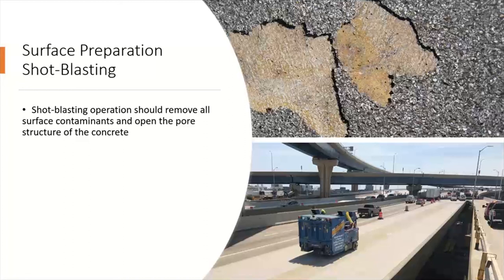The second thing that we noticed, and you might not know, but that amber color, we weren't 100% convinced that the first layer of the thin polymer overlay was mixed a little bit off ratio. But when you picked it up, you could poke it with a key or a fingernail, and you can see that first layer was soft. The second layer was hard, it was fully cured. The first layer wasn't. So two things went wrong. It wasn't mixed very well. They were using a mortar type mixer, and it was cold out there. Same thing, two things that I talked about that need to be considered.